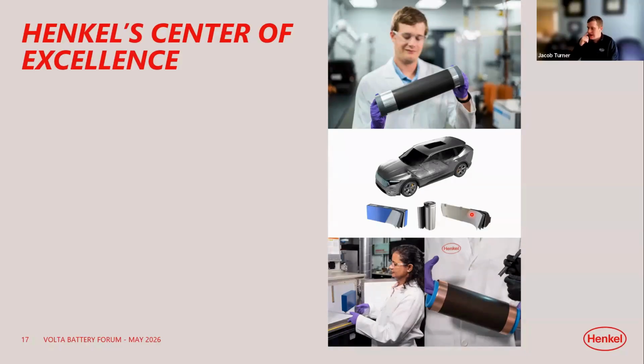Yes, good question. And I would say at its core, yes, it's similar in terms of the types of carbon. There's a little bit of difference though in terms of the amounts. When we start thinking of forming that conductive network in that DBE processing style, where we're also functioning as an adhesive, it requires different amounts of those non-conductive materials to be present in there. So it makes that formation of the conductive network a little bit more challenging. When you go to something like the 2000 series, forming that conductive network becomes a little bit easier. You can get away with higher loadings in that case. So I would say that's the challenge. The materials themselves are pretty similar in terms of what you would use, but you might need some other tools in cases to form that conductive network at different loading levels.